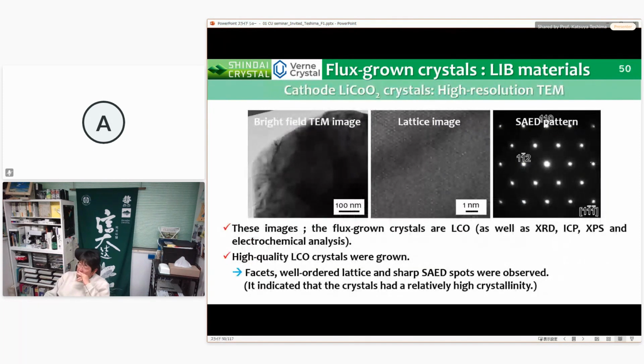These are the high-resolution TEM images. These images show the flux-grown crystals are LCO, with well-developed facets, well-ordered lattice, and sharp SAED spots, selected area electron diffraction spots, which are evidence of high-quality crystals.